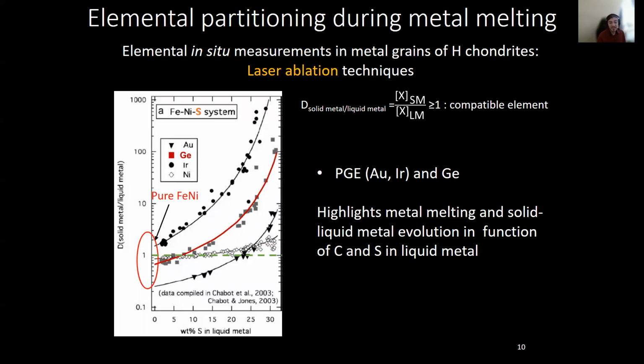So we have studied the repartition of siderophile elements in the metal grains to explore metal fusion and crystallization. Indeed, experimental studies show that elemental fractionation varies between elements and between liquid and solid. For example, if we consider a pure iron-nickel phase, iridium is a compatible element, whereas germanium is incompatible. But if we increase the percentage of sulfur in the metal phase, germanium can become compatible.